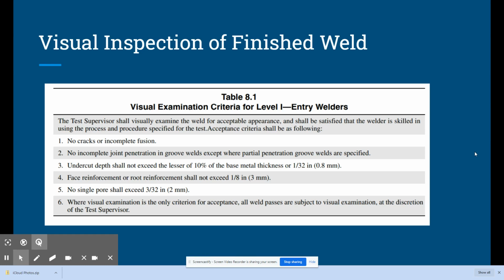Undercuts. Undercut is where we dig into the base metal next to the toe of the weld and never fill it back in. Very common on the top side for a horizontal weld because gravity's pulling that liquid metal away. But undercuts shall not exceed the lesser of 10% of the base metal thickness or 1/32 of an inch. Well, with 3/8 of an inch base metal thickness, 1/32 of an inch would be the lesser. So that's our standard we use. We'll check undercut, and it can be up to 1/32 of an inch undercut.